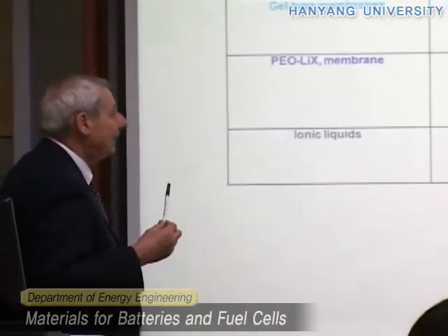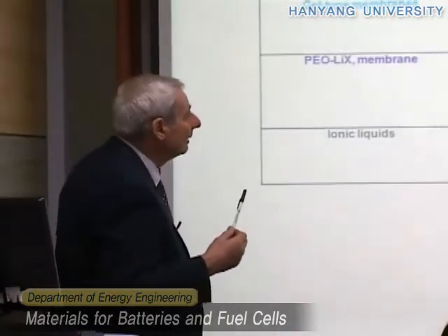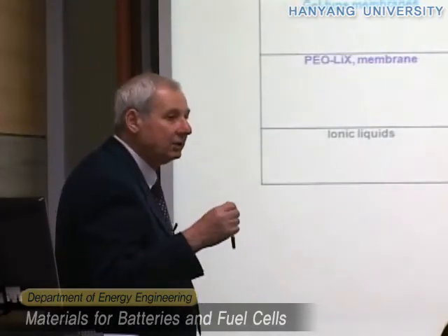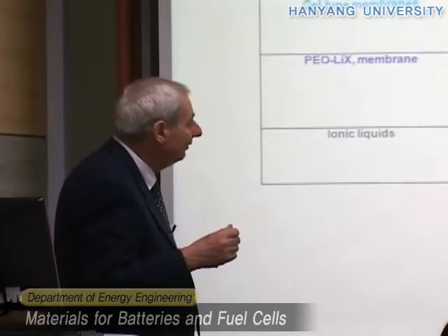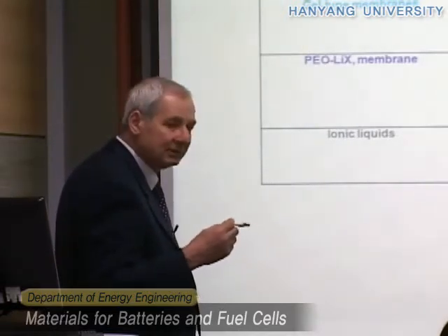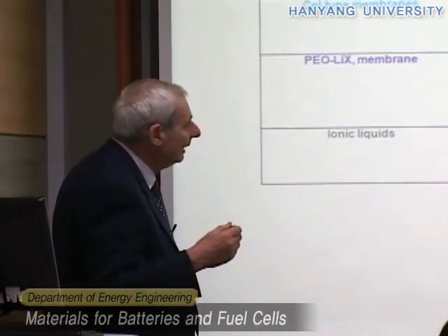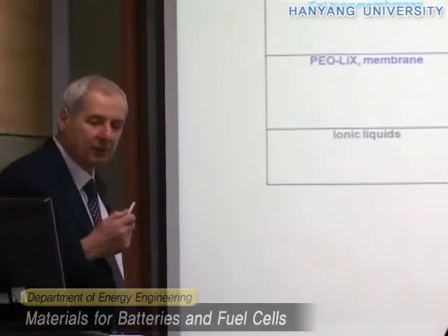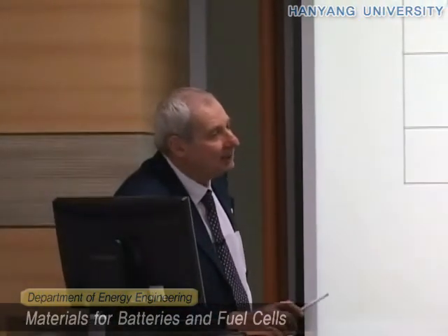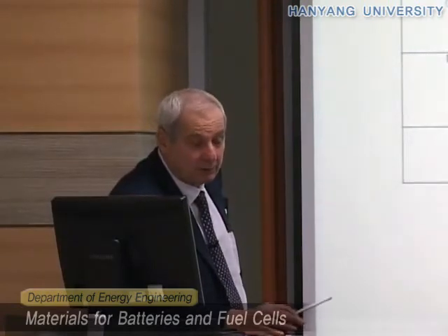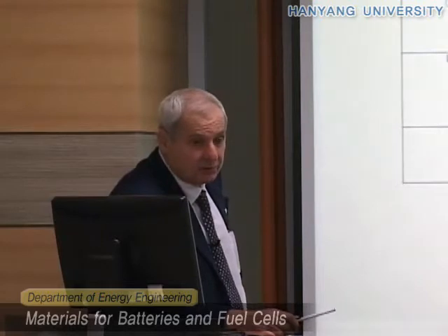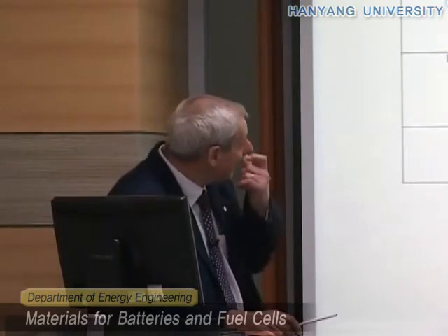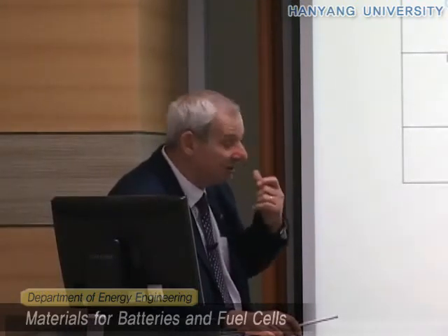But we have, at the moment, some temperature-dependent conductivity. The conductivity goes down below 80 degrees. The transport of lithium ion can be a little low, but this can be solved. And also a problem here that I forgot to mention before is that the anodic stability of this electrolyte is around 4.4 or 4.5 volts. So you can use electrode materials which are within this stability, and this is the reason why the most common cathode used with this electrolyte is lithium iron phosphate, which operates at 3.5 volts.